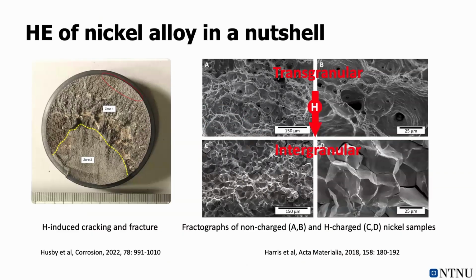Xavier has shown that in nickel alloy, when hydrogen enters the material, we have this fracture transition from transgranular to intergranular. A lot of previous work has demonstrated that experimentally. But the consequence is that in the early 90s, the oil industry believed that nickel alloys are hydrogen insensitive. So to avoid hydrogen embrittlement in steel, they used a lot of nickel alloy as fasteners in the oil industry, especially in subsea operation. Later it was demonstrated that nickel alloys, with time, also became hydrogen sensitive. So how to deal with that is an issue nowadays.